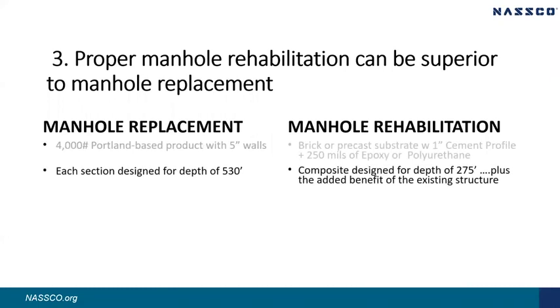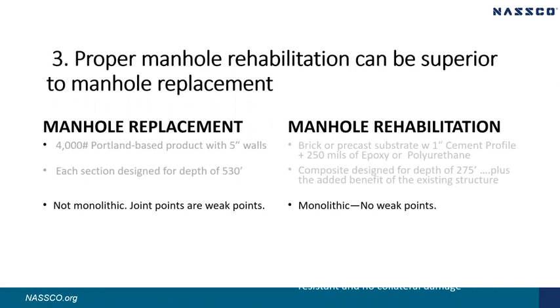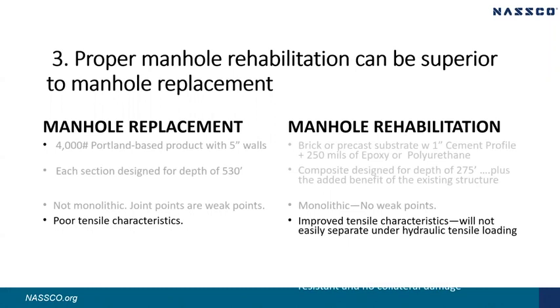In the case of replacement, each precast section is designed to a depth of 530 feet. Conversely, the cement profiling plus 250 mils of epoxy or polyurethane can perform down to a depth of 275 feet, plus the added benefit of the underlying structure. The rehabilitated manhole will enjoy monolithic strength and cohesion, whereas the precast sections will suffer from weak points at each joint. The monolithic nature of the rehab manhole means that it will enjoy improved tensile characteristics and will not easily separate under hydraulic loading. I have seen precast cone sections separate at the barrel sections due to hydraulic uplift. This happened to manholes in a city in southeast Tennessee near the Tennessee River during a flood event.